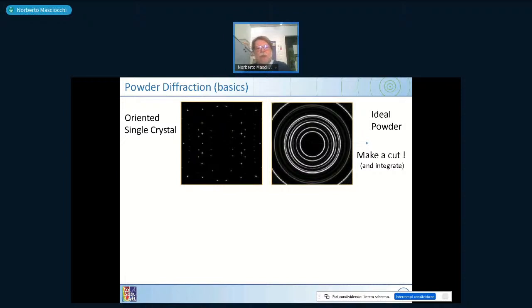And so this is a real picture. This is a real picture of a powder. On the left, you have a single crystal. On the right, you have a powder. You can see that the rings in the powder are not complete. For example, the central ring has some failures here and there, so the intensity is smaller. The second ring has smaller intensity than the right side, so that means that this is not so ideal, meaning the orientation of the crystallites is not so random, but there is some preferential orientation. This is something one should avoid. The rings should be equal in intensity and equal in distance from the center, so that any cut you make in any direction gives you the same powder pattern.